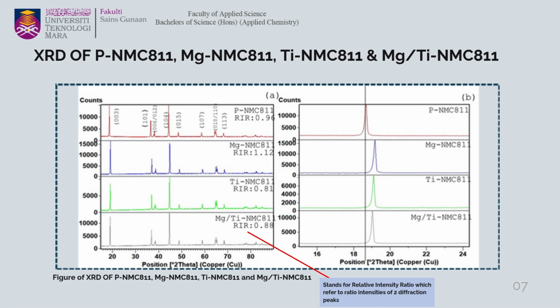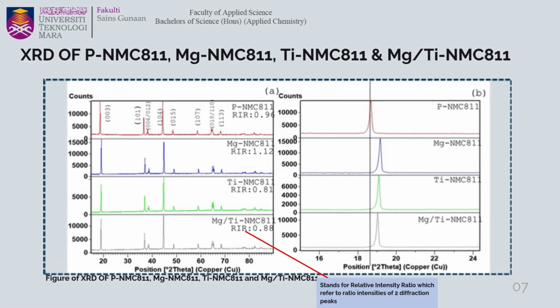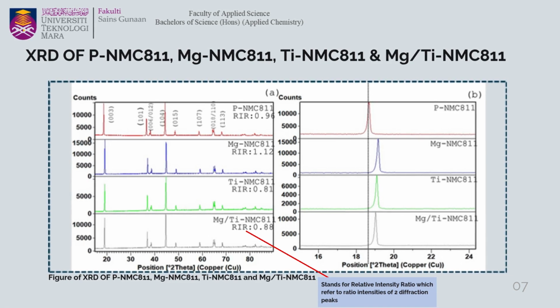Okay, the next slide is the XRD of pristine NMC, magnesium NMC, titanium NMC, and co-doped NMC. It is shown that all the samples are pure because all the peaks are identical to the pristine NMC 811. So it means all the doped samples are pure phase. And also the RIR value: only magnesium is improved because the peak at 104 is much shorter than the peak at 003. So this might be because of the reduction of cation mixing. Meanwhile, for the titanium and the co-doped NMC, the value is lower than magnesium. So based on all these peak splittings, there are no issues.